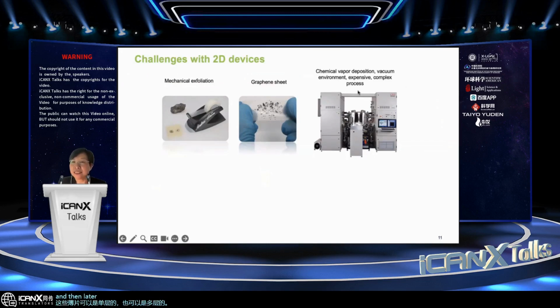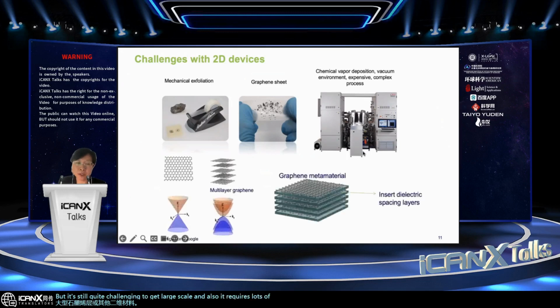Later on, very sophisticated machines were developed using chemical vapor deposition. You can get large scale graphene layers or some other two-dimensional materials. But it's still quite challenging to get large scale, and it also requires lots of expertise. How to make monolayer graphene or monolayer 2D materials with controlled layer number and large scale is really very challenging. In particular, in lots of devices you need multi-layer stacking to achieve very nice performance. However, the CVD method makes this very difficult.